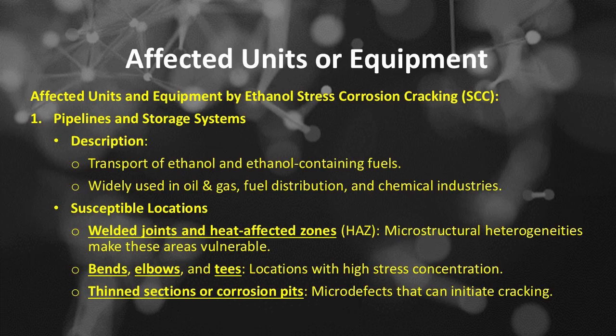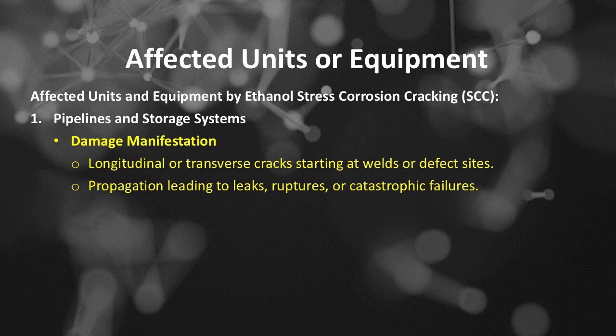Affected units and equipment by ethanol stress corrosion cracking include, number 1, pipelines and storage systems, includes transport of ethanol and ethanol-containing fuels. Widely used in oil, gas, fuel distribution, and chemical industries. Pipelines and storage systems. Susceptible locations include welded joints and heat-affected zones. HAZ microstructural heterogeneities make these areas vulnerable. Bends, elbows, and tees, locations with high stress concentration, thin sections or corrosion pits, microdefects that can initiate cracking. Pipelines and storage systems. Damage manifestation includes longitudinal or transverse cracks starting at welds or defect sites, propagation leading to leaks, ruptures, or catastrophic failures.